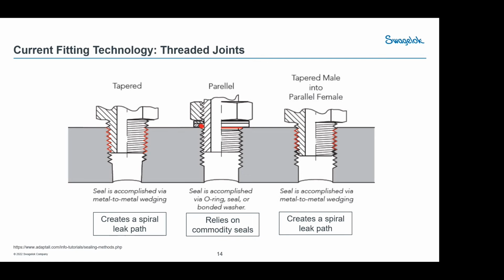What we found is that high quality NPTs that are designed to work with each other and follow high tolerances are important. Where the threads are manufactured appropriately, they will give you the best wedging, what's called metal to metal wedging, taking place in those threads. The Teflon fills in the continuous pore structures, but the Teflon tape can't get pushed out like the liquids can. So we do find that 1/4 and 3/8 inch work the best. 1/2 inch can start getting to a point that there's just too much surface area to overcome, and above that, they can be problematic. They can also be problematic on remake. So tapered are out there, they're not the best.